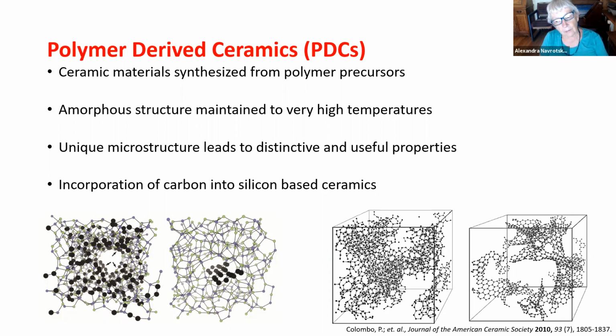No, the carbon doesn't do that. The carbon substitutes for oxygen. One doesn't have silicon nitride, silicon carbide in the material. One essentially has silicon that is bonded to 4 oxygens. That's the usual tetrahedral network silicon, or silicon that's bonded to 3 oxygens and a carbon, 2 oxygens and 2 carbons, etc. And one can tell the difference and actually count up the number of species, especially by nuclear magnetic resonance spectroscopy. Some of the more sophisticated forms of NMR also give you some spatial resolution that tells you that the number of these mixed bonds, the number of these silicon carbon bonds, is greater near the edges of a fragment of this silica framework. The nearer you are to the carbon phase, the more carbon you have in the silica phase.